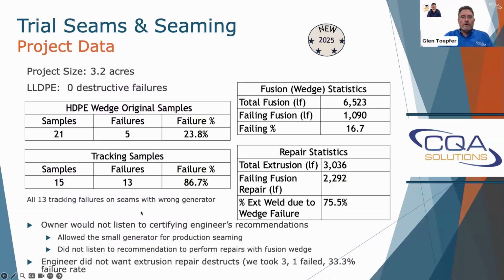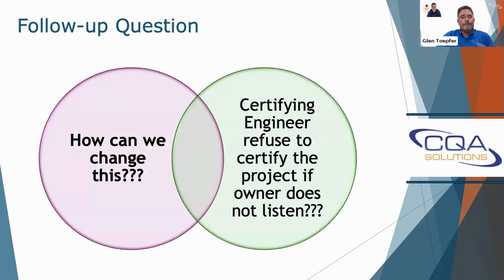The repairs. I mean, they should have avoided it in the first place. That would have been the best thing to do. But once we had it, the problem's twofold. You had the failures, and then you had the extra repairs. And it was basically the owner wouldn't listen to the certifying engineer's recommendations, both for the small generator and repairs with the fusion wedge. And then the engineer didn't want to take the extrusion destructs, but we managed to talk him into taking three, and one of those failed. And it just shows you, we typically see 15 to 20% average failure on extrusion welds when they're taking on repairs.